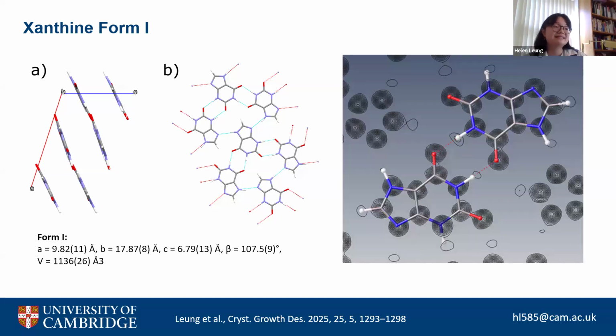What was very cool about our data is that xanthine has tautomers, so the position of the hydrogen can flip between the 2 nitrogen positions on the molecule that you see here. Our 3D ED data was of high enough quality that we could distinguish the tautomers and confirm that we had the 7H tautomer, which just means we could see very clearly where that hydrogen was. The resolution of our data, I think we cut to 0.9 angstroms, gave us an R factor of about 10.9%. So that was very promising and very cool to see.